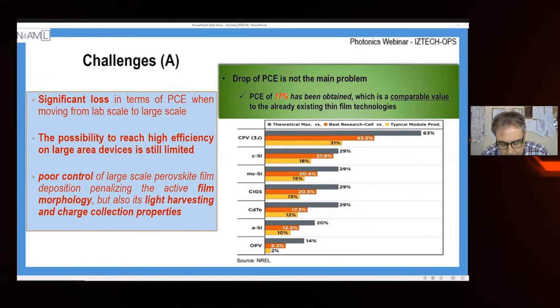Usually, we have poor control when we try to apply the perovskite material from the lab size, which is very, very small, to, let's say, a stripe of 20 centimeters. When we think that 20 centimeters can be 1 meter, of course, this is a more difficult thing. I mean the film morphology and how we can achieve a homogeneous and fine crystalline material in large area. I think that it still needs some good progress and some new ideas.